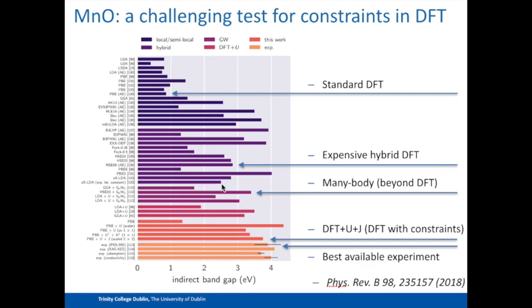You push up the average value, but you still have a big spread. And you can even go beyond density functional theory to Green's function-based methods that are getting very, very expensive, and still you do quite a poor job. So this is where we come in, my research group. What we've been developing for the last few years are these methods to, on a case-by-case basis, measure the error in density functional theory. We measure the strength of its breach of certain known quantum mechanical exact conditions, and by hand, really with sort of cheeky pen and paper tricks and code hacks, we put the right physics back into density functional theory. I mean, there's a lot of technical detail under the bonnet, and it's actually quite a rigorous thing, but this is where we are in practice.